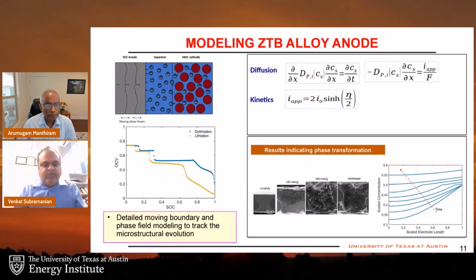And we also tried to model this next generation battery material by looking at the microstructure evolution inside this battery, in this anode material. We see that when you charge and discharge this battery material, there is hysteresis. And in addition to that, the morphological change makes a difference in terms of the performance of the battery. So we developed an electrochemical continuum model for this device, and that is able to predict this charge discharge curve with reasonable accuracy. And the next step would be to take this to battery management systems to identify the charging protocol for this chemistry. Thank you.